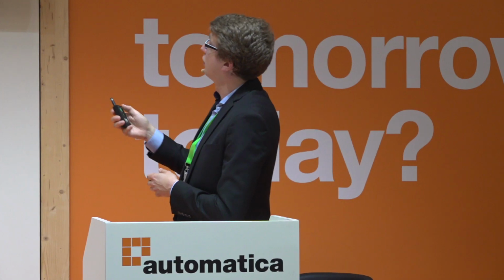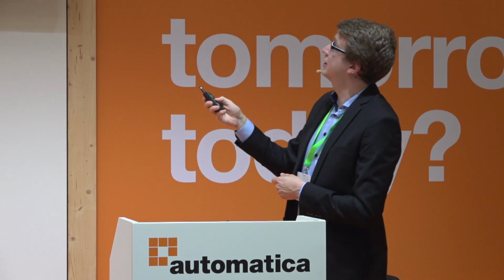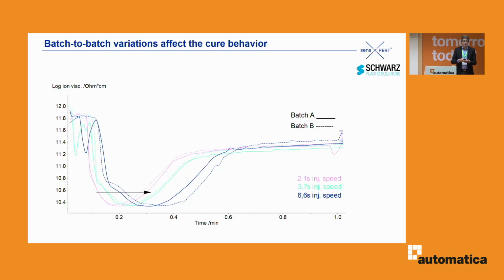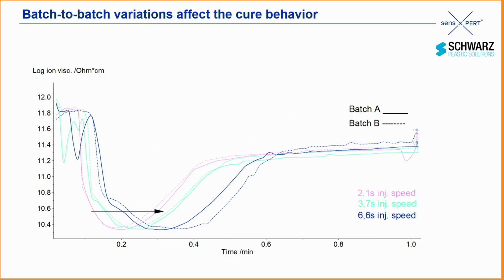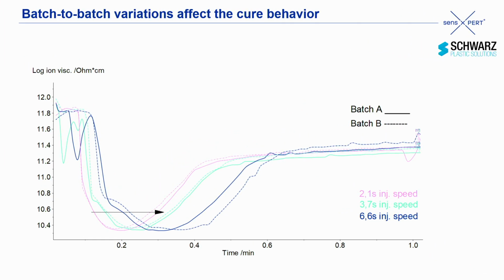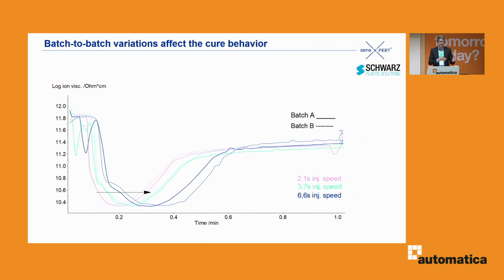And so if we throw two different batches of material, two different bags basically, into our plastics manufacturing machine, we are going to see a different behavior. As you can see, in some cases, if we have high injection speeds, the entire reaction is shifted to faster behavior. If we have slow injection speeds in the first place, the reaction kinetics are slower. So this is really an influence that is hard to pin down, but here we can actually measure it and react to it.